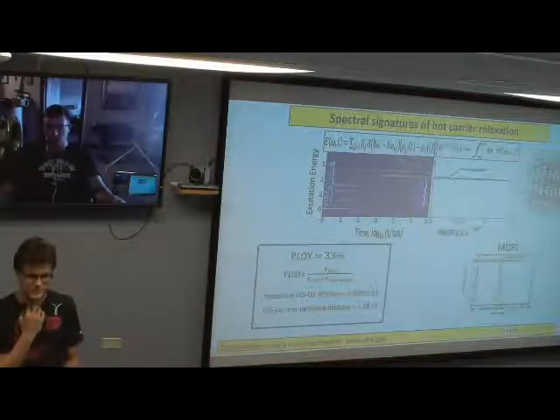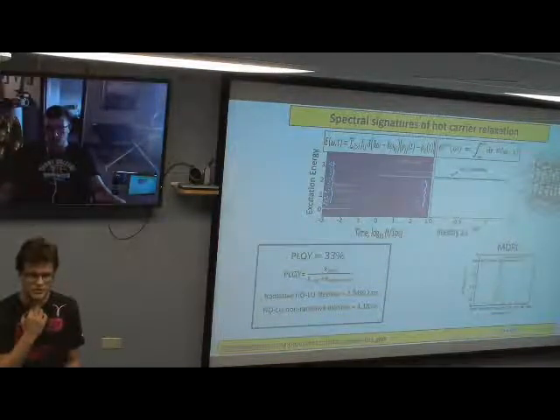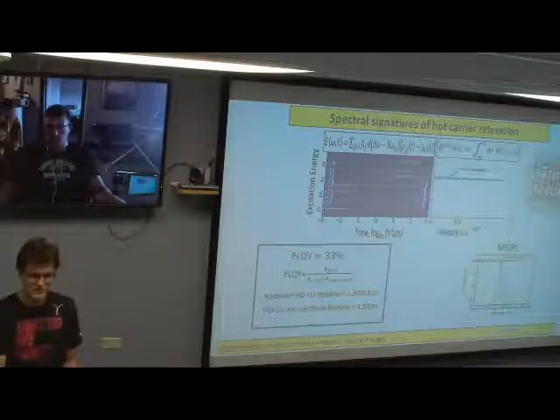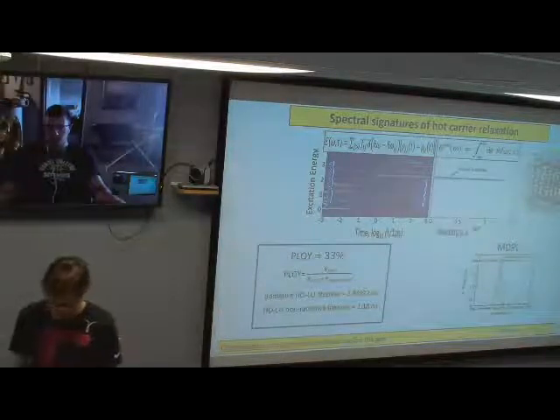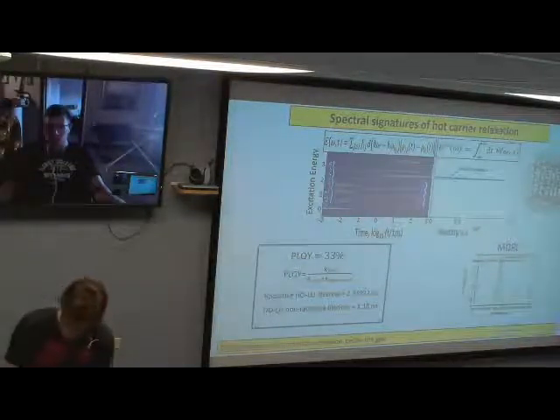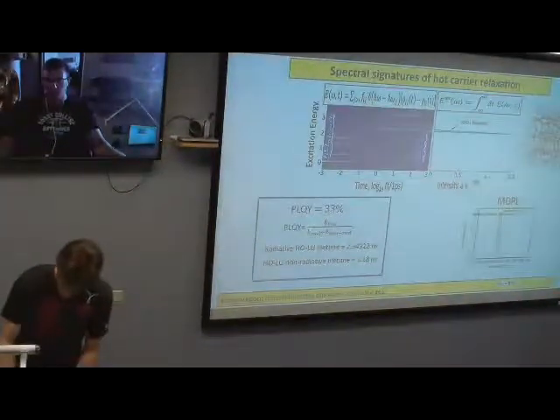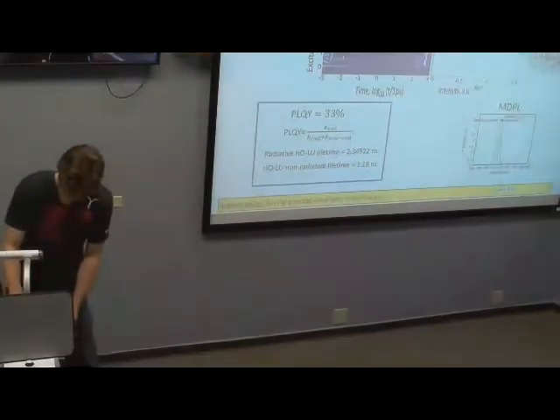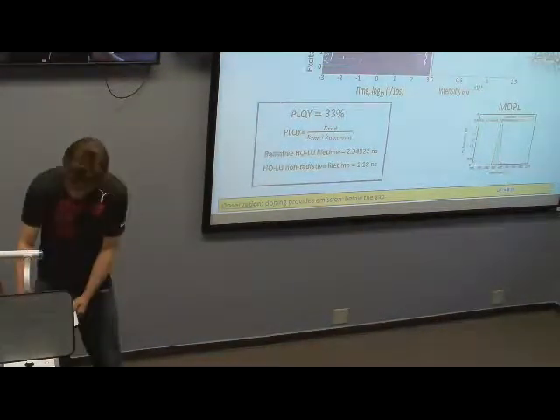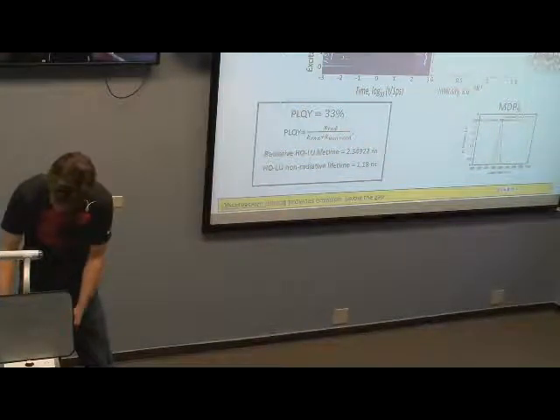because we don't include any sort of correction for the Rashba effect, which has been a popular theory which explains why the non-radiative relaxation is suppressed in these systems. And if you're not familiar with what the Rashba effect is, I'll just draw a little diagram. So basically, from earlier, this is what you expect for a typical band structure for any material.